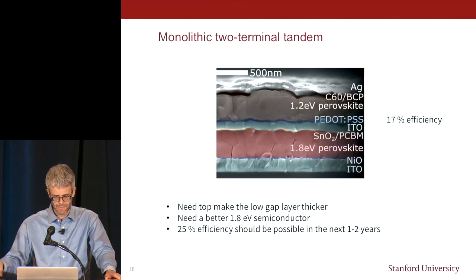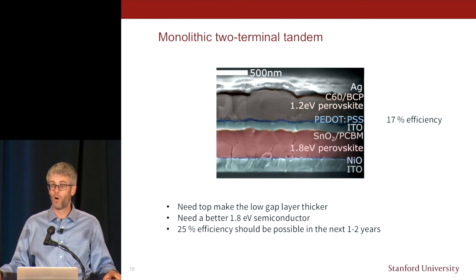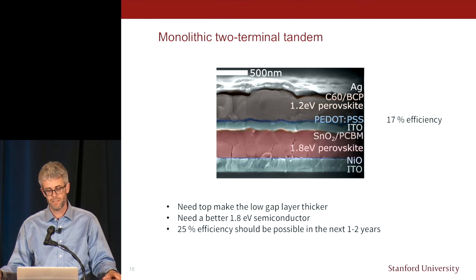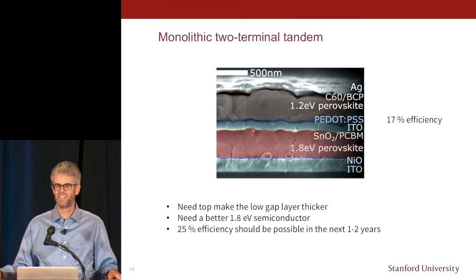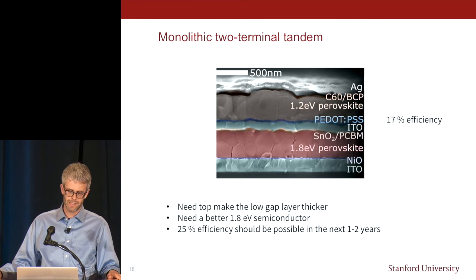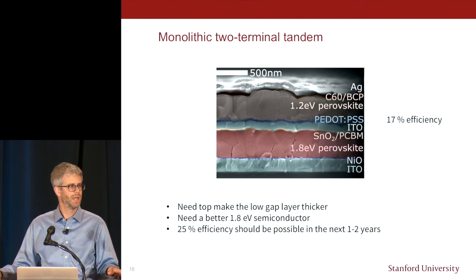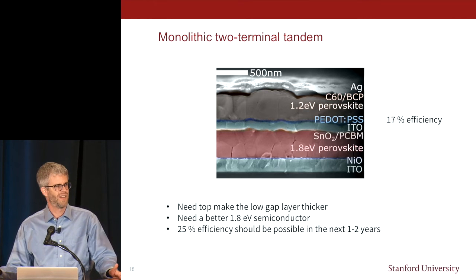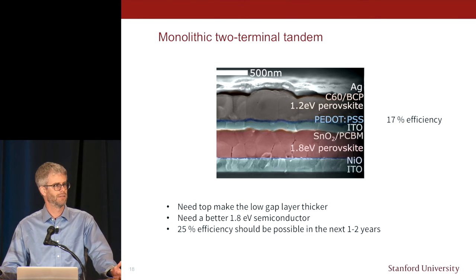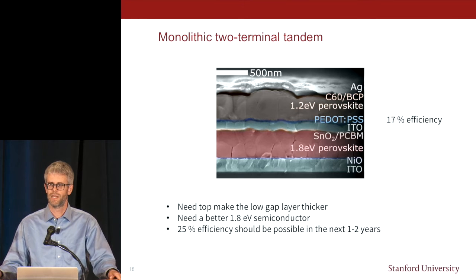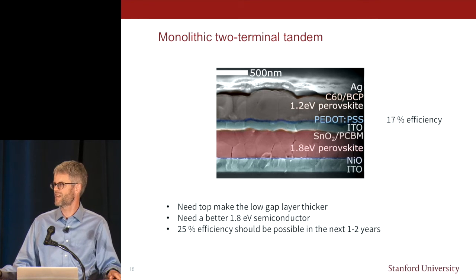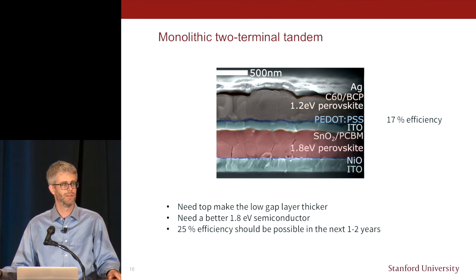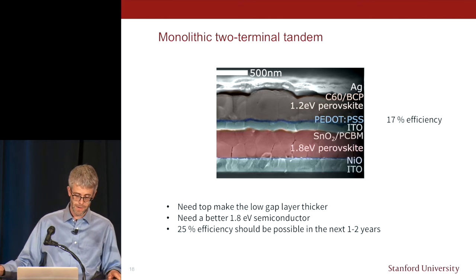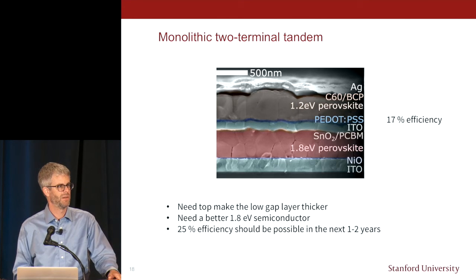And this is an SEM of an all perovskite tandem, and this first one was at 17%. And we will be able to do way better when we just figure out how to make this new material thicker. It has very low voltage loss, and we just haven't made it thick enough to absorb all of the light. So I'm very optimistic that could go up to 25% fairly soon.